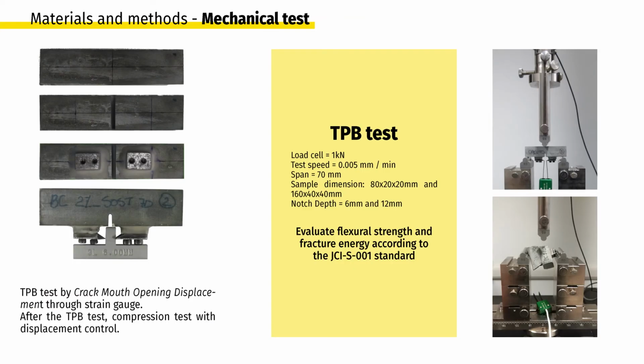Once the maturation and curing were finished, a U-shaped notch was made in the middle of each specimen, and the three-point bending test was carried out, performed by controlling the crack mouth opening displacement and using a strain gauge, with the aim to evaluate the flexural strength and fracture energy.